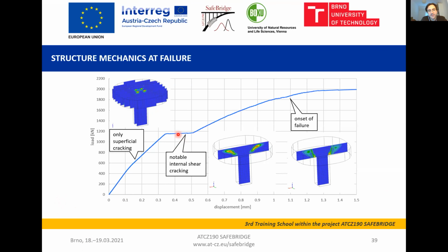And then we can see the load increase further until eventually the structure starts to fail. Like at the third image, we can see the failure happens adjacent to the pillar. So this is also in line with what a conventional calculation according to Eurocode would yield, where the most critical failure mode, or the most critical check, is the shear adjacent to the pillar. Next slide, please.